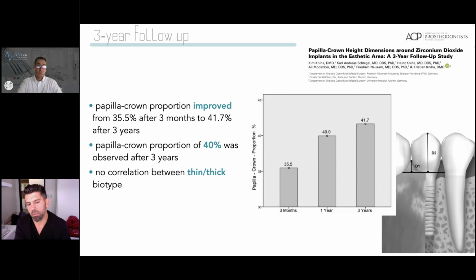And this is important because one of the biggest advantages that we are seeing with zirconia is the behavior of the soft tissue around these implants. Even in patients with thin biotype, where sometimes you would expect recession to occur, the tissue stays very stable around these implants. And as we'll see, zirconia allows the soft tissue to adhere to the surface. So there's a direct connection mimicking what we see on natural teeth between soft tissue and zirconia.